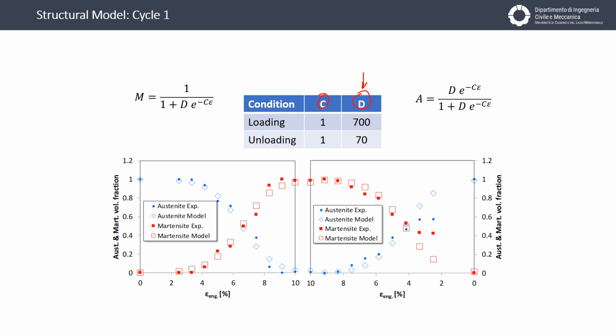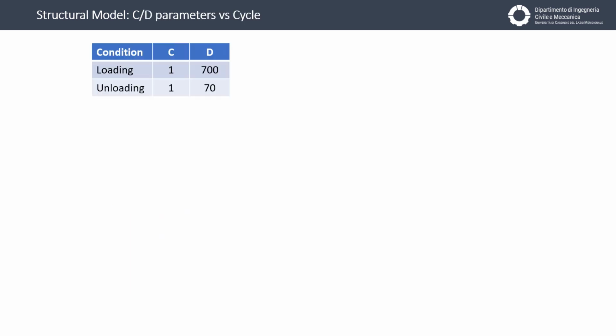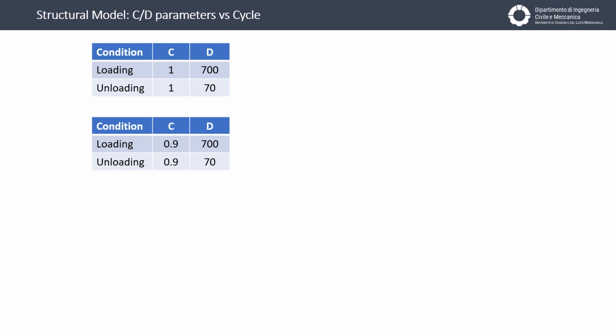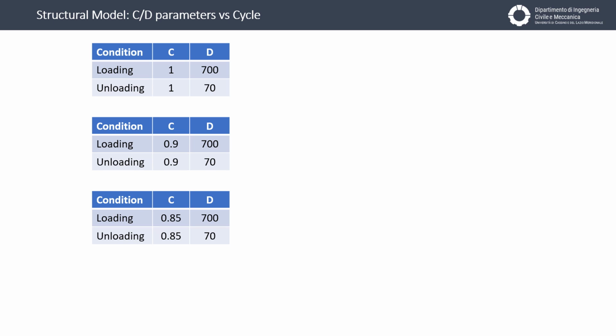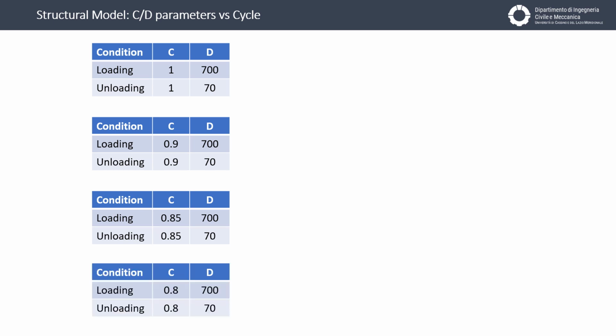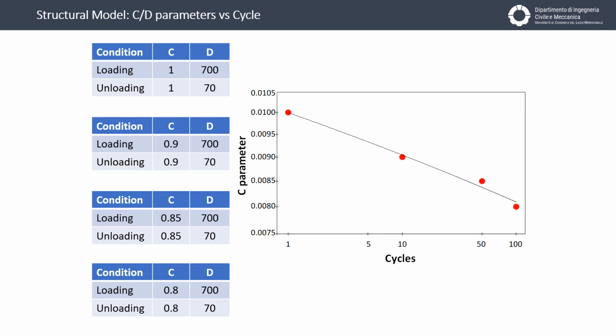In the graph you can see how the plotted functions seem to fit well the quantity of measured microstructures. Calculating the parameters not only for the first cycle but for the 10th cycle, you can see that the parameter C changed from 1 to 0.9 and the parameter D is always the same in the loading and unloading conditions. Next, at the 50th cycle, the parameter C decreases again, and after 100 cycles it decreases too. Plotting the parameter C in terms of the cycles, you can see a behavior like this. It means that the parameter C takes into account a sort of fatigue effect in the shape memory alloys.